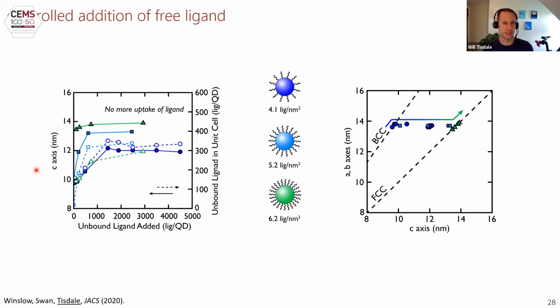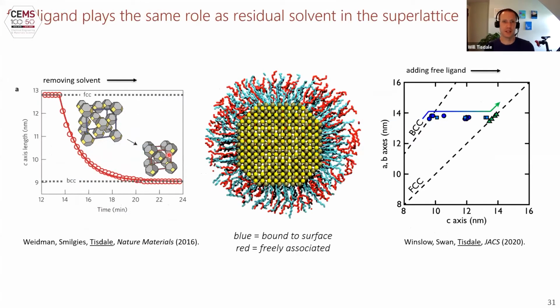Interestingly, not all of the free ligand gets incorporated into the unit cell. There is a period where adding unbound ligand expands the lattice, and then there's a point where you hit saturation, and the more ligand you add, you can't further increase the lattice constant of the superlattice. So the really striking thing here that we thought was that this march through phase space that the system takes as you add more and more free ligand is exactly the reverse process we saw during the in situ X-ray scattering experiments removing solvent. So here, as you remove solvent from the lattice, you go from an FCC to a BCC in a uniaxial contraction. Here, as you're adding free ligand, you're going from BCC to an FCC, again, as a uniaxial expansion.